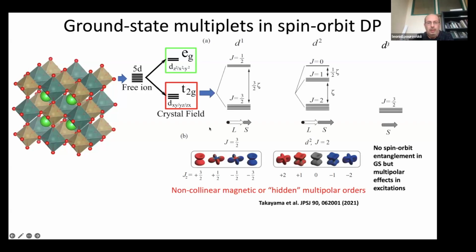For example, if one puts one d electron, one has, of course, the Hund's rule state maximizing the pseudo-orbital momentum and the spin, and they will add up, giving us effective J equal 3/2 for the ground state. And if we go to d2, then with the same arguments, we get the ground state having J equal to 2.